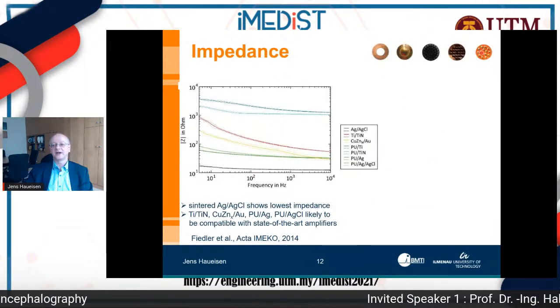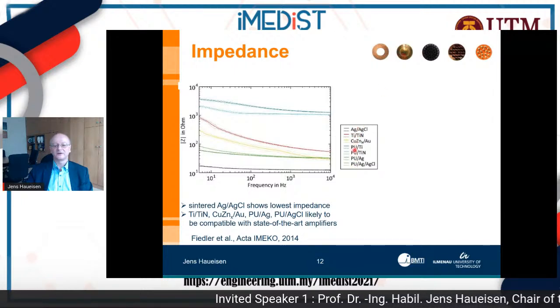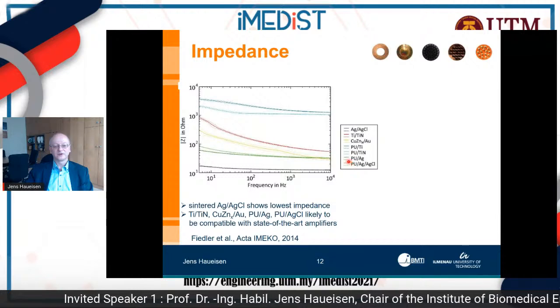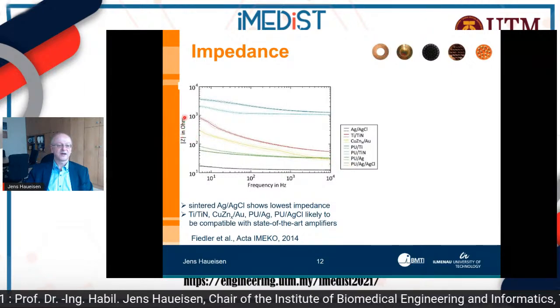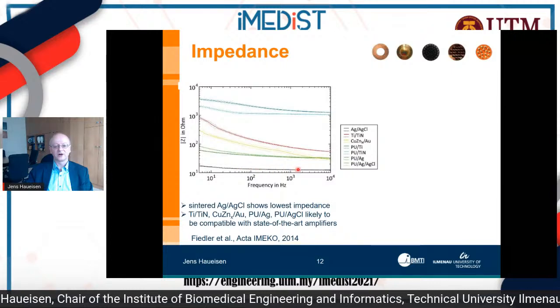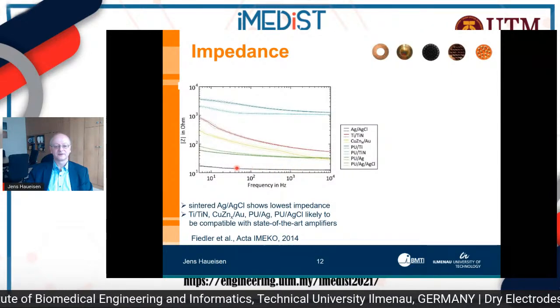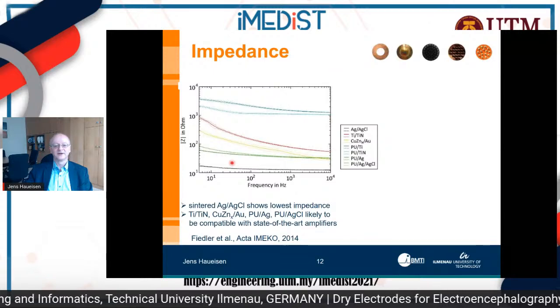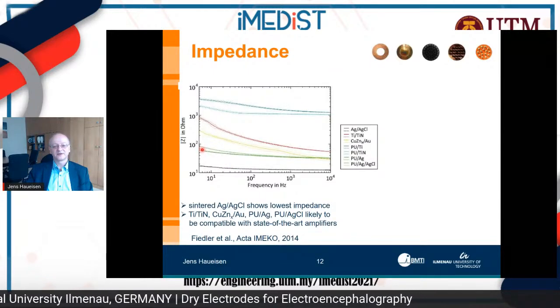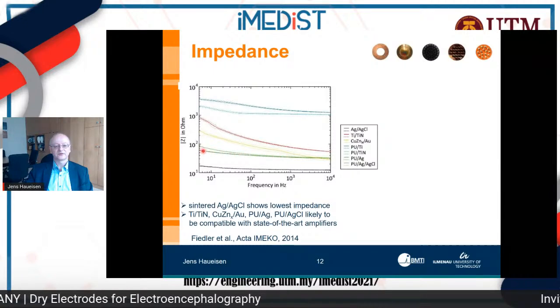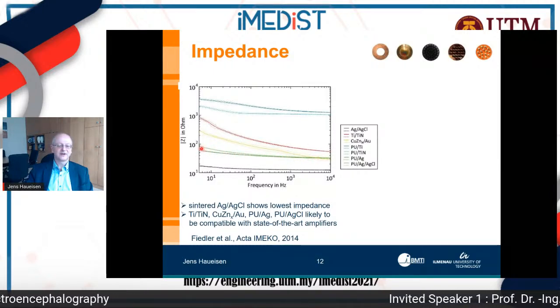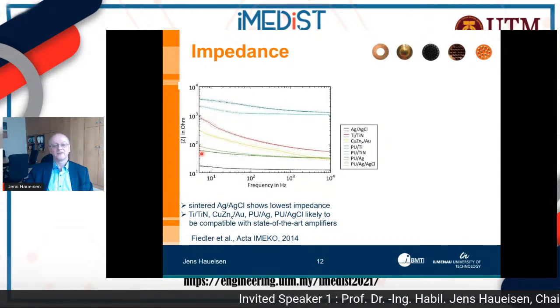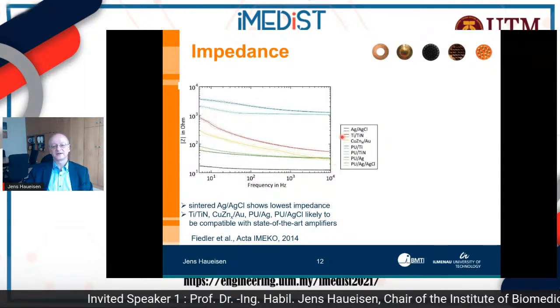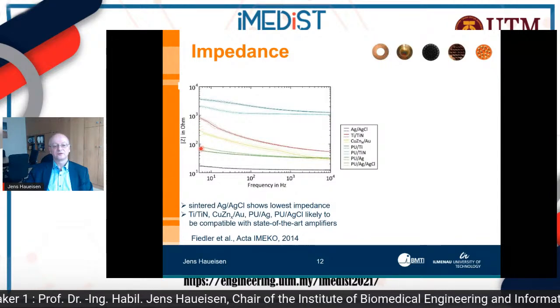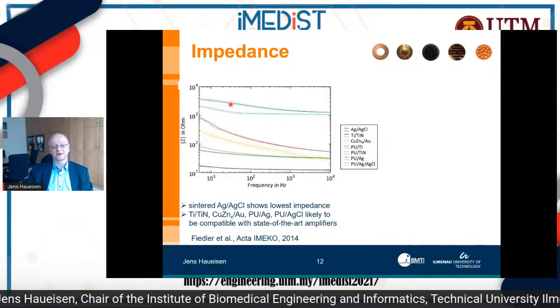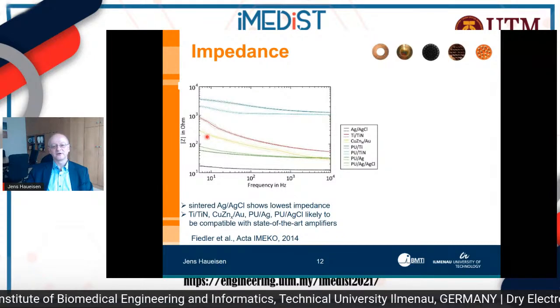So you see up here the different electrode types, and you see they are color-coded in this legend. What you can observe is, of course, that the absolute value of the impedance is lowest for our gold standard electrodes, so the silver chloride electrodes, the classic ones basically. But you can also observe that for the silver coated polyurethane electrodes, we have also a relatively low value. And more importantly, the standard deviation, so standard deviation means always the dotted line, is relatively low compared to all the other types of electrodes, which we see here. The worst one is actually the gold pin electrode.